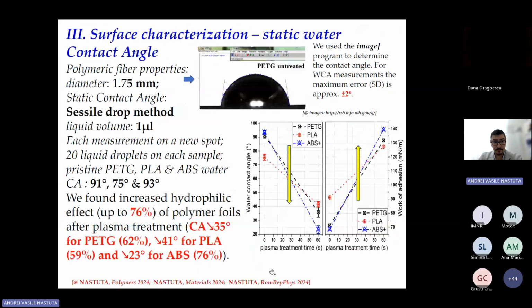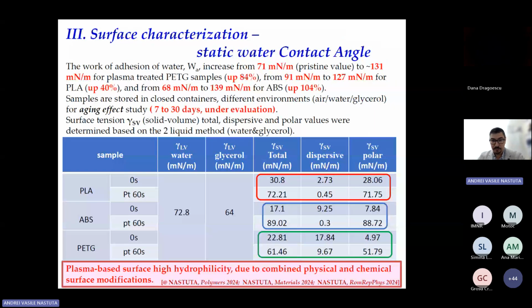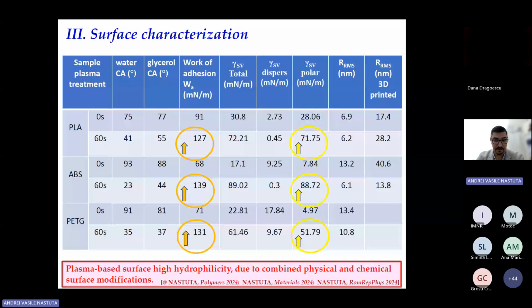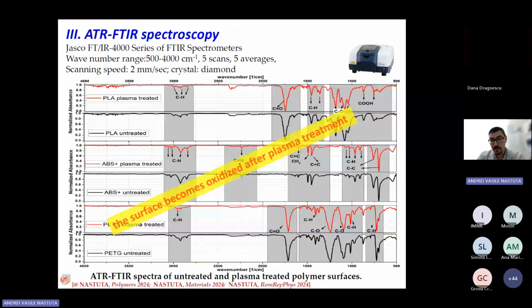Of course, we are interested also in the surface, and we saw that every time we are treating the surface, the water contact angle is decreasing and the energy of the surface is increasing. That means that the surface is more hydrophilic, more stickable to the next layer. That thing is, let's say, to be seen in the surface tension on the total value or even on the polar part. We can correlate this with the time of the treatment of the surface. And of course, we can also somehow relate it to the oxidation process that we can see during the FTIR spectroscopy as well.